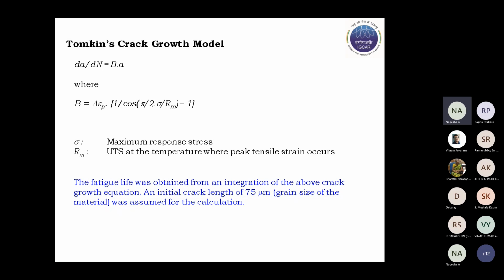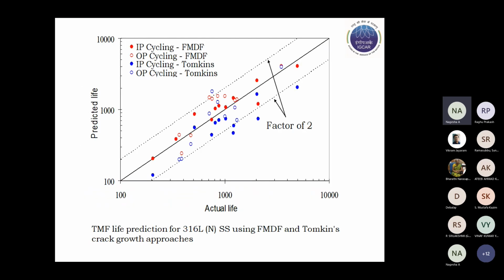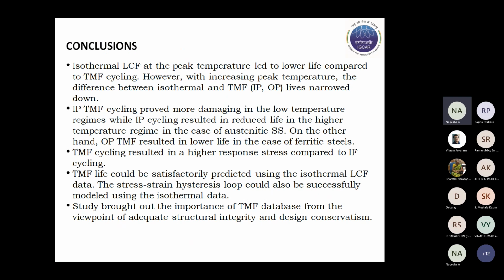So which was found from the tested samples, where we have seen that when the crack length reaches 1.2 mm, the fracture of the sample happens. So that was taken as the final crack length, and we can see that both these techniques gave rise to prediction of cyclic life largely within a factor of 2, for both the 316 LN SS. And now, just to conclude my lecture.